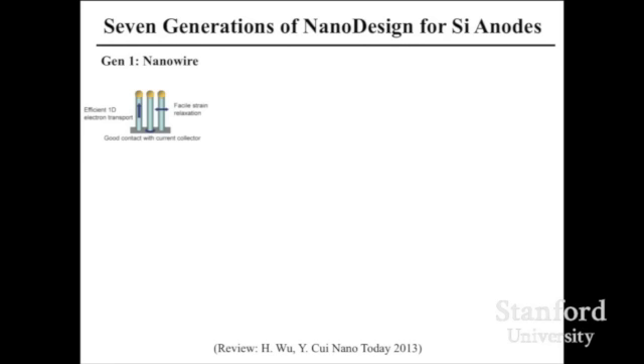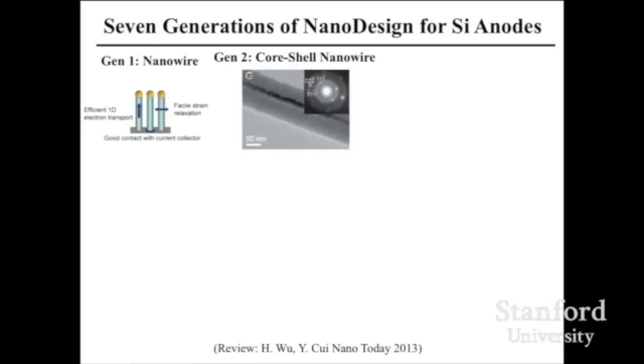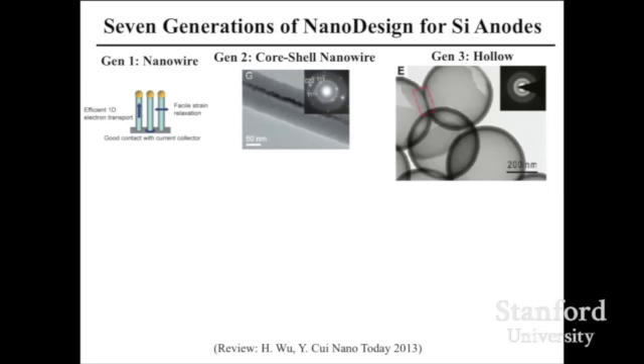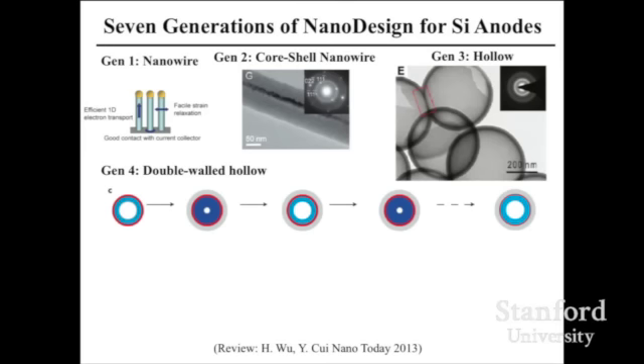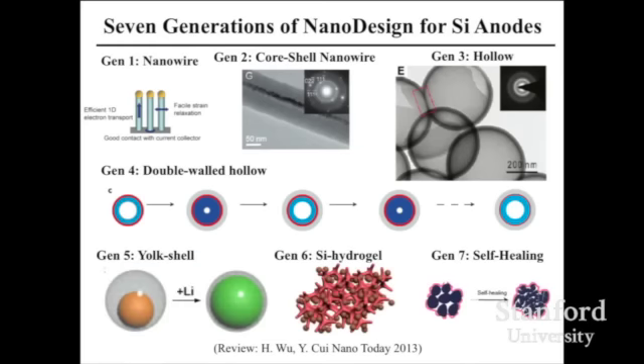So through several years of understanding, we started from silicon nanowires. We moved on to generation two, making core-shell wires, with a stable core and amorphous shell. The stable core maintains mechanical support and keeps moving electrons more efficiently, which improves the batteries. We also went to hollow nanoparticle structures, using the interior surface to relax the strain without breaking. So it's improving year by year. Then we went to the double wall hollow structure, and I will tell you why. Later came yolk shell, silicon hydrogel, and then self-healing. Now it's generation seven. This month we are going to have generation eight coming out, but I'm not ready to release this yet.